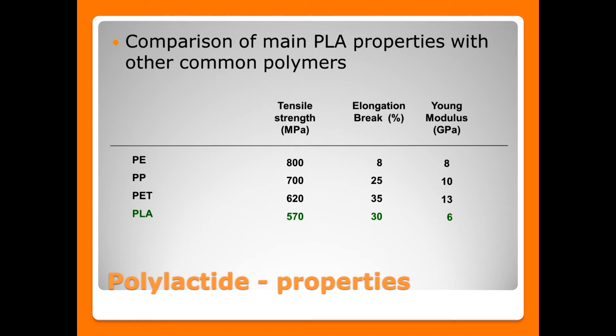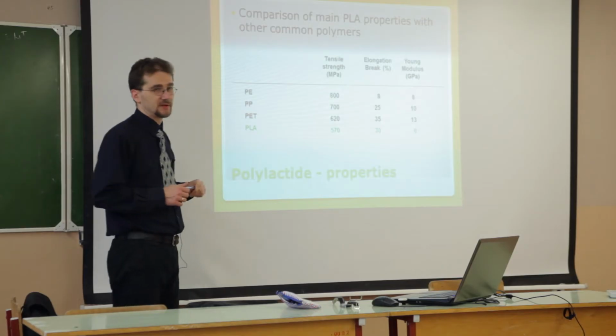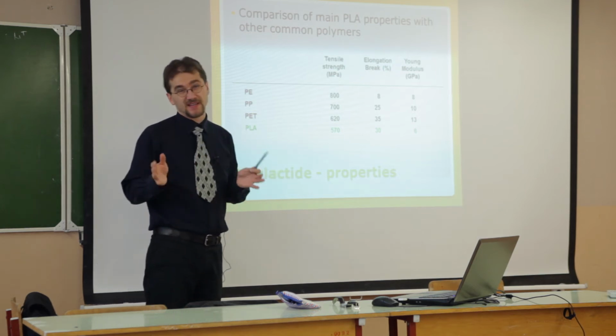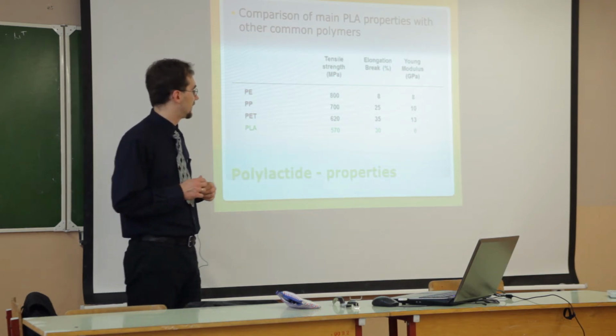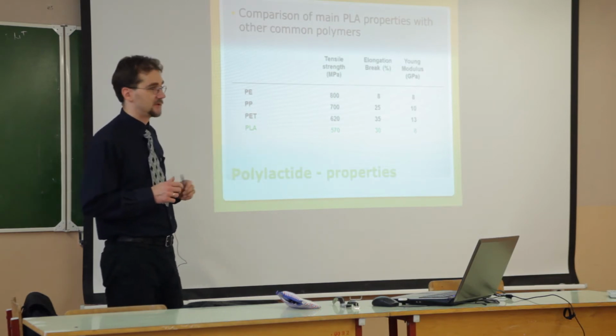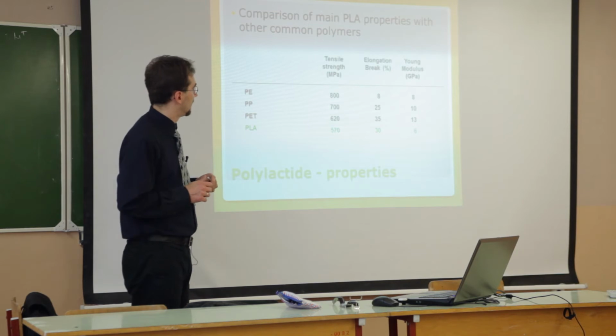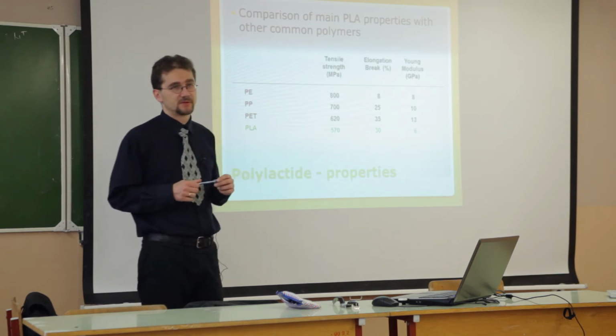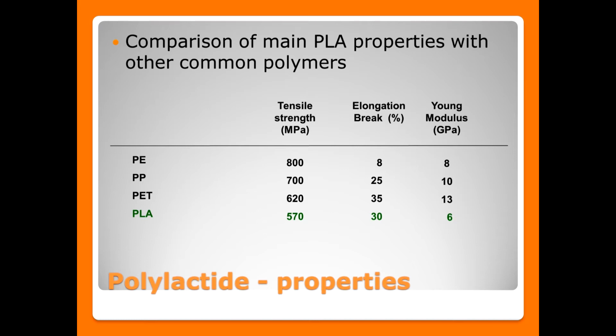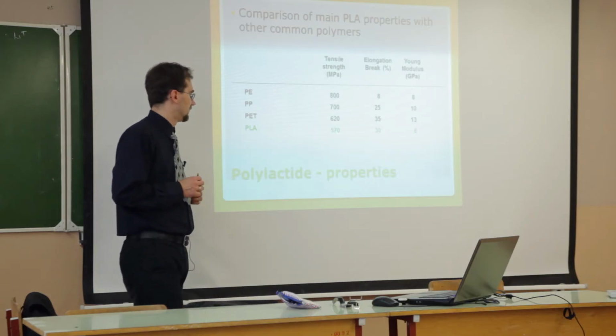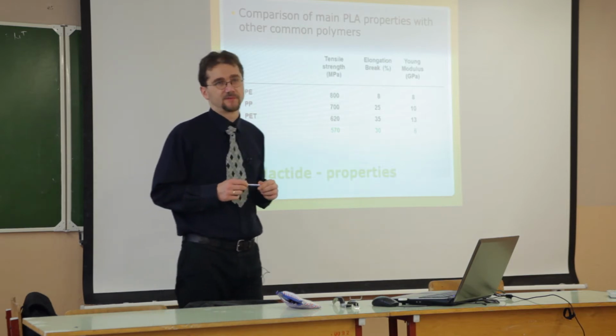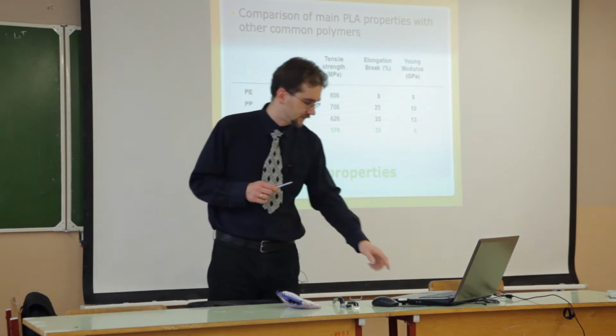Tensile strength in megapascals for polylactide is 570, so it's slightly smaller than polyethylene, polypropylene, and polyethylene terephthalate, but it's in the same range, I would say. Elongation at break is 30%, between polypropylene and polyethylene terephthalate, and Young's modulus is close to polyethylene. So it's not bad. Maybe in some aspects it will not be enough, but generally we have to admit that we can produce polylactide with quite good mechanical properties.